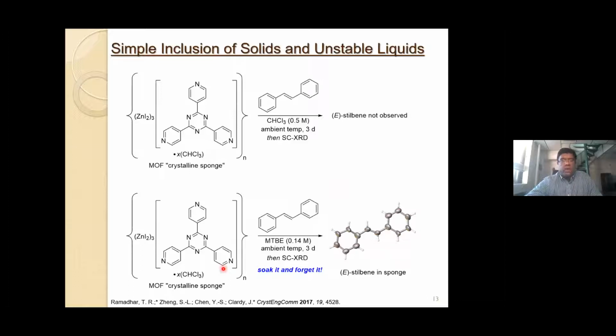One other thing that we wanted to do was to try to include solids, amorphous solids, and unstable liquid organic compounds inside of the crystalline sponge. So I wanted to try to include E-stilbene, which was the bane of my existence for a while as a postdoc. I had E-stilbene basically saturated in chloroform, added that to the crystalline sponges, let that soak for 3 days at room temperature, and I was never able to observe E-stilbene. But I thought about the problem a little more, and I thought, well, I'm using chloroform, and that's a pretty polar solvent. It's a good solvent for E-stilbene, but perhaps it's too good of a solvent. So maybe E-stilbene's going inside of the sponge, but the chloroform is going to help to solvate it and prevent it from forming good intermolecular interactions with the host framework, and you won't be able to see it because it's going to be way too disordered.